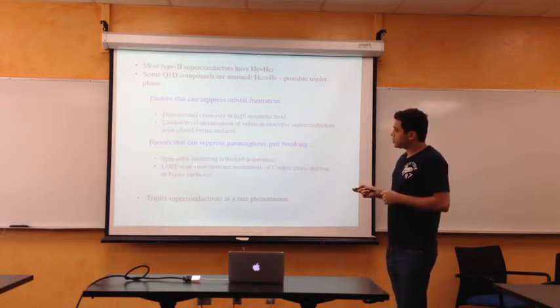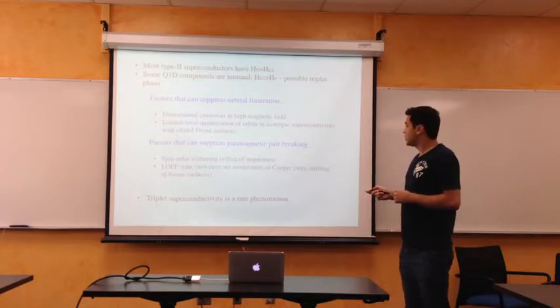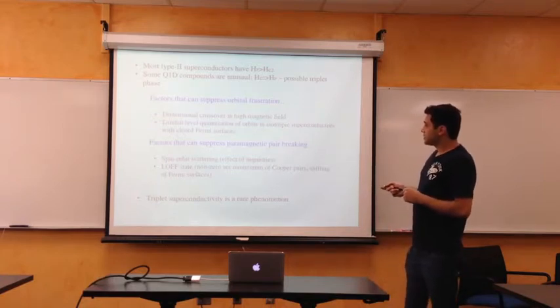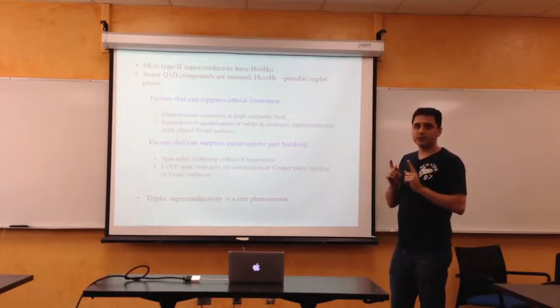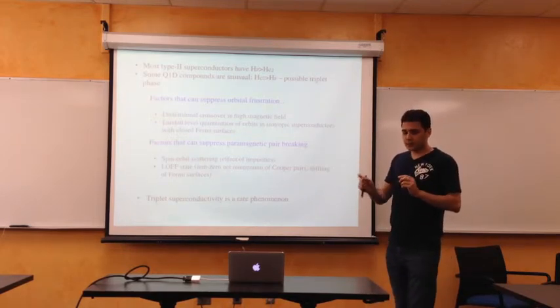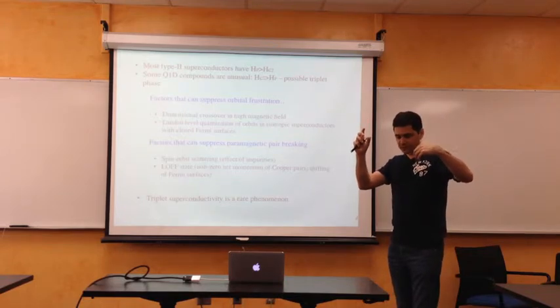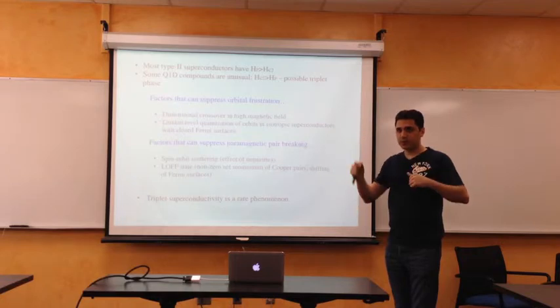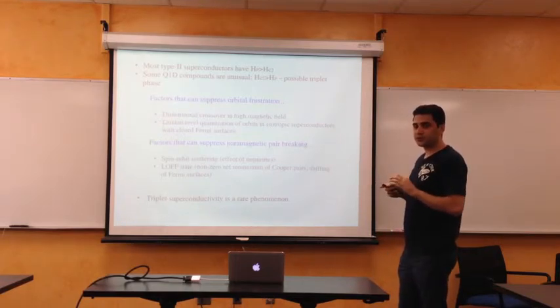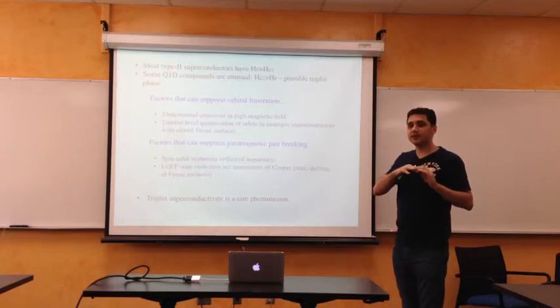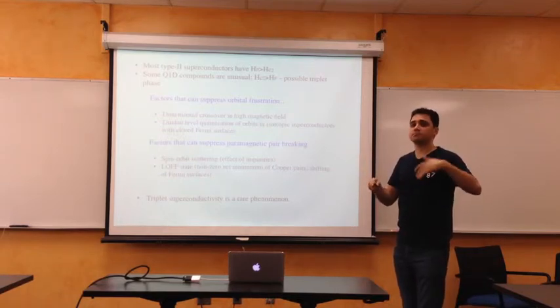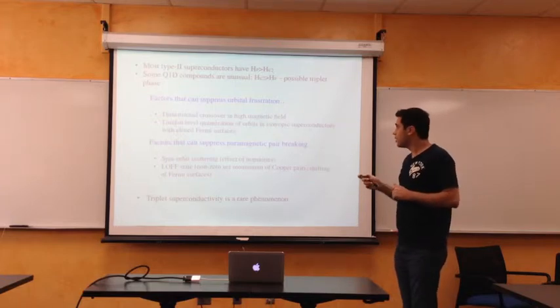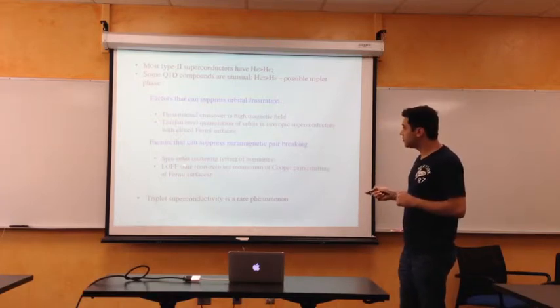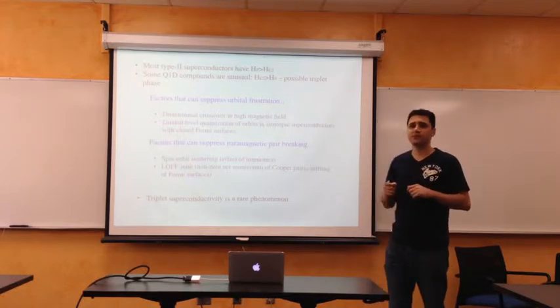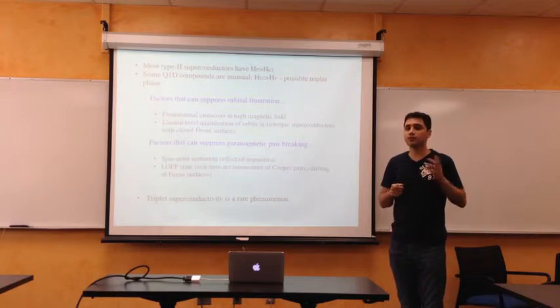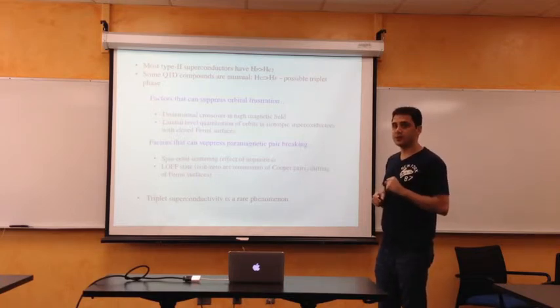Another possibility is the so-called LOFF state. This is a special case where the Cooper pair acquires a non-zero net momentum, and the electrons paired on Fermi surfaces actually shift with respect to one another. That results in the suppression of Zeeman splitting, so superconductivity can persist for fields higher than the Pauli limiting field. We specifically calculated the limiting field for this case, and it turns out to be about 5 to 6 Tesla, which is still 3 times smaller than what we're observing experimentally.